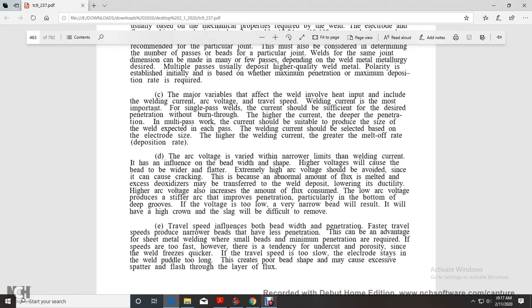The arc voltage will vary within narrow limits of the welding current, influencing the bead shape. Higher voltage will make the bead wider and flatter. Extreme high arc voltage should be avoided, since in this case cracking can occur because too much flux has melted. Excessive deoxidizers may be transferred to the weld deposit, lowering the ductility at higher arc voltage, or increasing the amount of flux consumed.